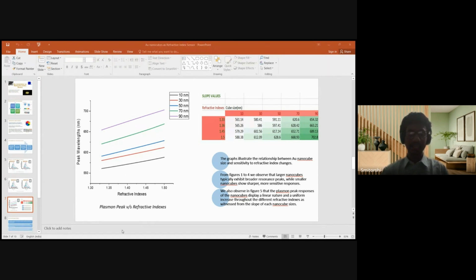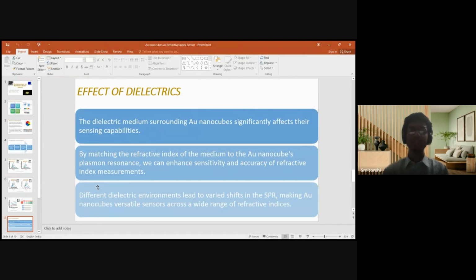Also, a factor that governs these effects is the dielectric medium that surrounds it. It significantly affects the sensing capabilities. By matching the refractive index of the medium to the Au nanocube's plasmon resonance, we can also enhance sensitivity and accuracy of refractive index measurements. And different dielectric environments lead to varied shifts in the SPR, making Au nanocubes versatile sensors across a wide range of refractive indices.